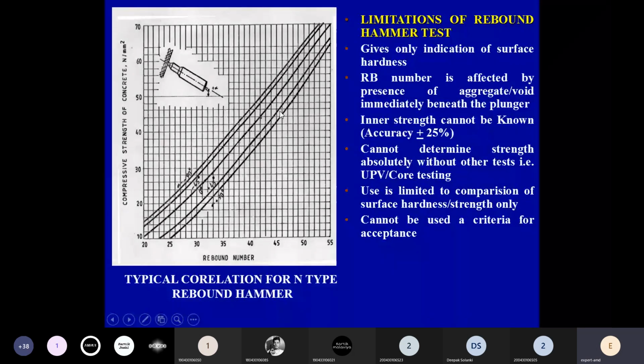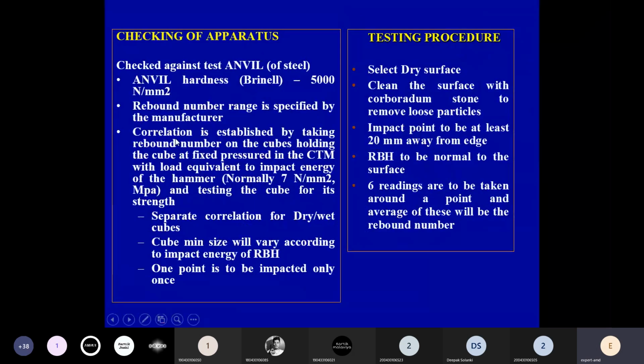But the point is that this curve is prepared by the manufacturer on a particular set of materials, a particular type of aggregate, a particular type of cement, etc. So if you want a more accurate assessment, there is a method given in IS 516 to calibrate the hammer in your lab itself. What is that method? You need to cast a cube of that particular grade of concrete which you are going to use in your structure at the mix design stage itself. So we cast a cube of M25, M30 grade concrete. We place it in the CTM machine, the compression testing machine, and we apply a load of 7 Newton per mm square, which is roughly 16 ton load, something like that.